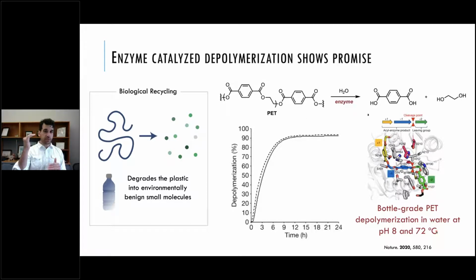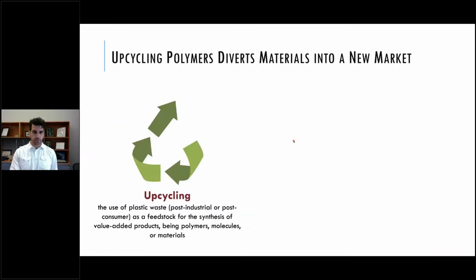However, if you heat enzymes up too much, they degrade, right? So this enzyme is actually engineered not only to depolymerize PET, but also to be as thermally stable as possible, to be able to heat it up to a temperature where you can get pretty reasonable rates of depolymerization. So this is certainly not ready for prime time, but I think it's a really interesting research avenue. And the last part of my general topic, I'll talk about upcycling.